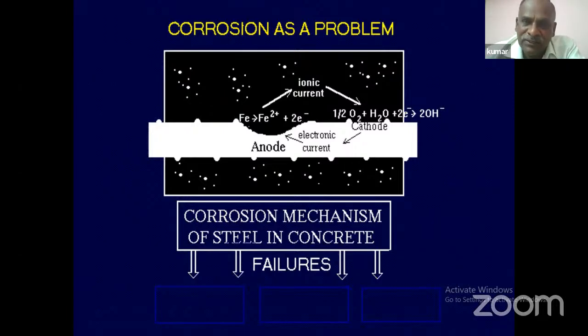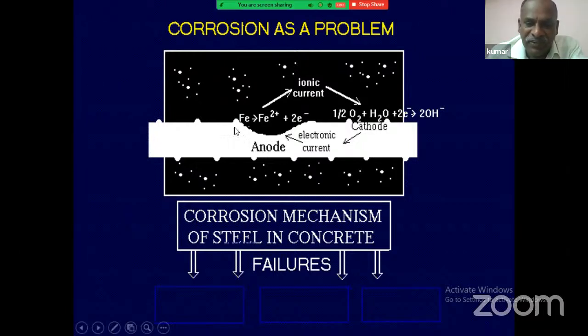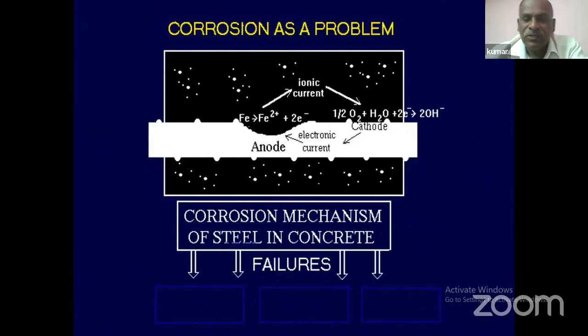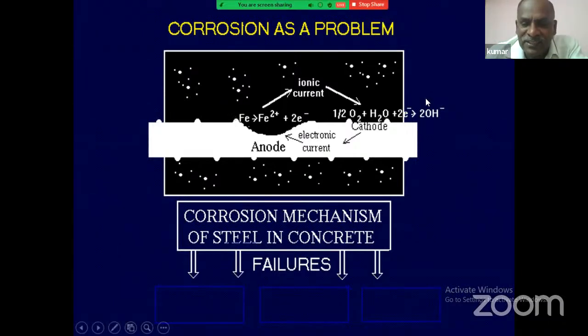So the chloride available in that seawater is penetrating. Why is it penetrating? That also I explained. The Cl minus has an affinity towards the ferrous ions. Here, Fe has the 2 plus, Fe 2+. So the Cl minus always has an affinity to attach to the ferrous ions. So this is the way general corrosion is happening. Even without chloride, the corrosion is happening.